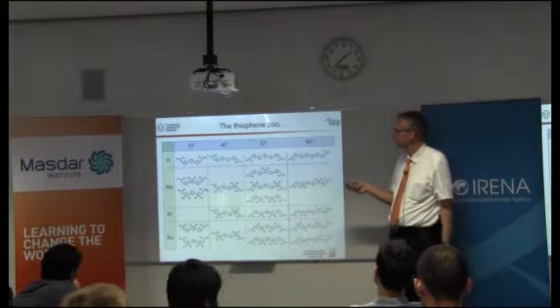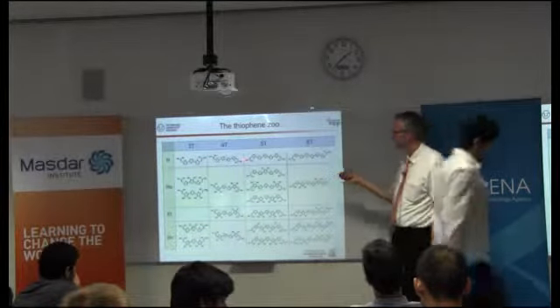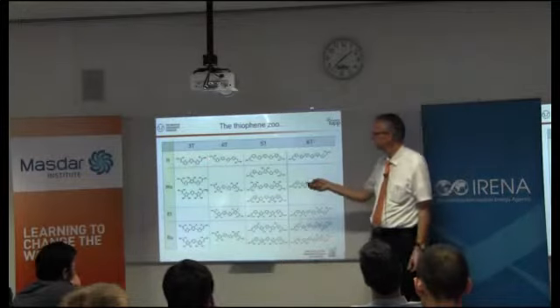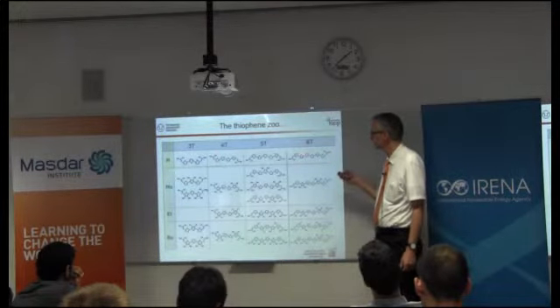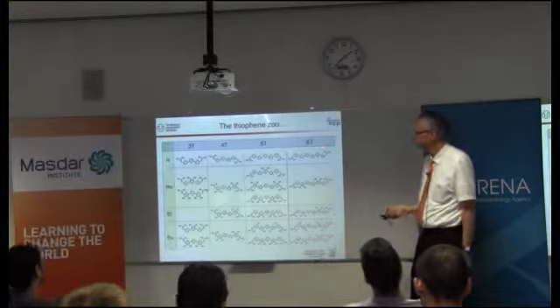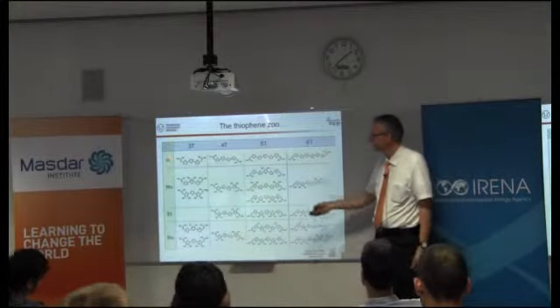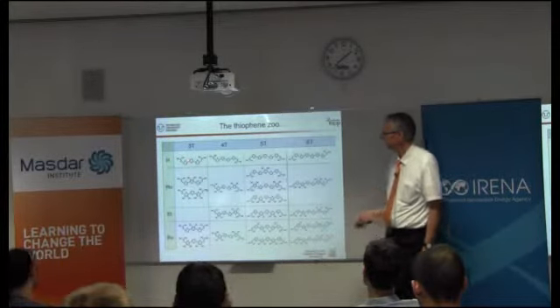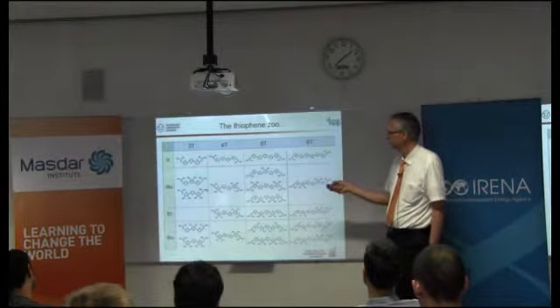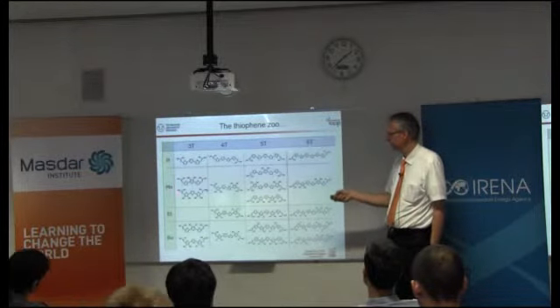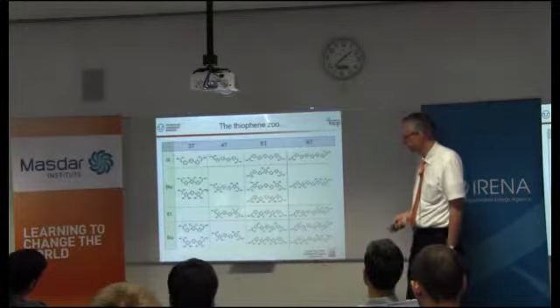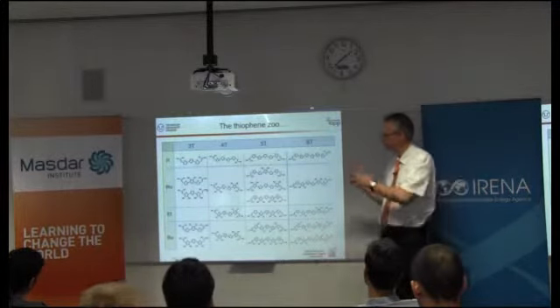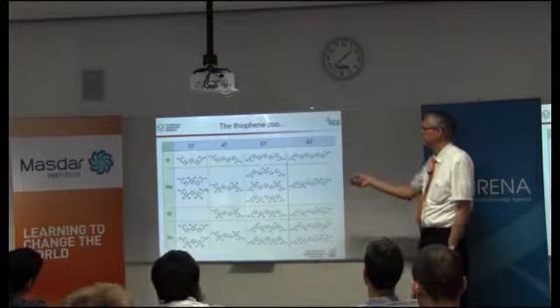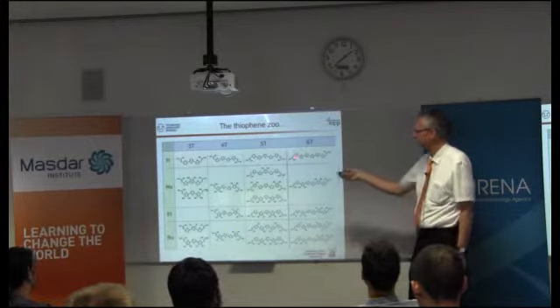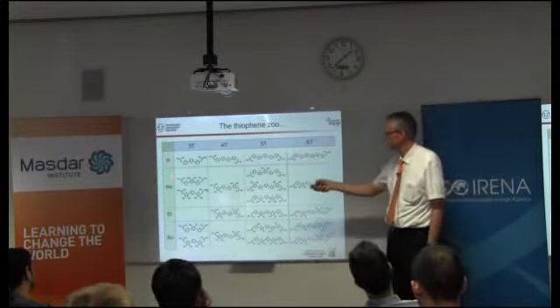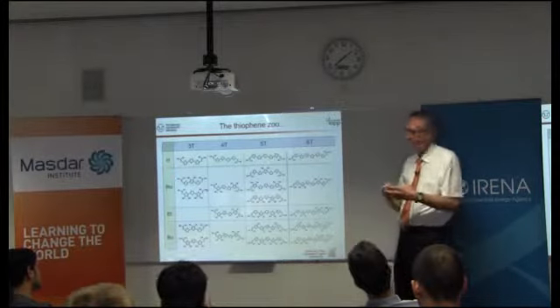And what we did is we looked at these thiophenes, and we varied two things. We varied the number of thiophene rings in the molecule from 3T to 6T. And we varied the side groups. There are certain side groups in either molecules with hydrogen, methyl, ethyl, or butyl side groups. And this way you have a beautiful handle, because with this coordinate you change the energetics of the molecule, and with this coordinate you change the crystal packing.